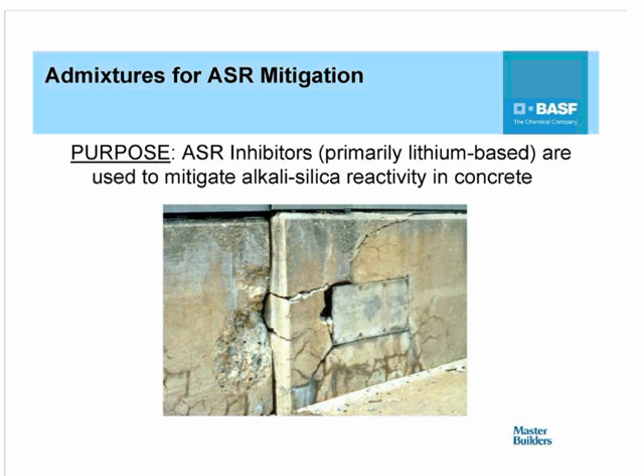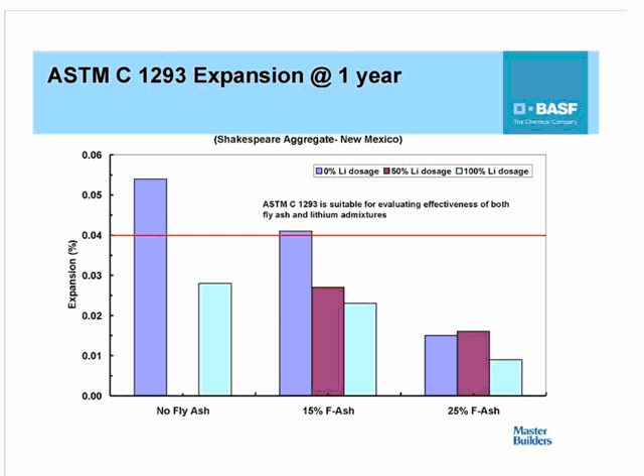Let's start off with the admixtures for mitigation of alkali-silica reaction. Now, alkali-silica reaction is a very destructive reaction that occurs in concrete due to a reaction between the alkalis in the cement and reactive silica that may be present in some of the aggregates that are used. There are various ways of mitigating alkali-silica reaction, but from an admixture perspective, lithium-based admixtures are very effective in doing so, as shown in this particular graph.